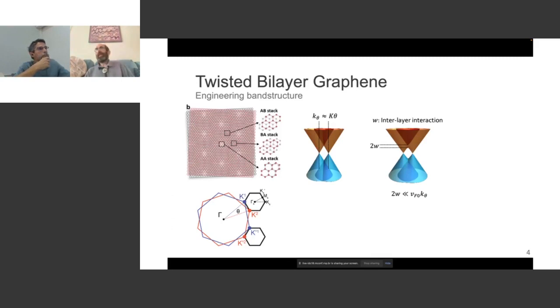So why is that more than a curiosity? It's because having energy independent of momentum upends the paradigm that we use to understand electrons in ordinary metals or semiconductors. So ordinarily, we have energy that is a strong function of momentum, a strong function of wavelength of the electrons in the system. And what that means is that if we have a certain number of electrons filling a material, they will fill all the kinetic energy states, all the energy states in this sort of band structure up to a certain energy, and then you run out of electrons. So all the states below are filled, all the states above are empty, and that turns out to be a very powerful way of understanding electronic properties of materials. But if energy is independent of momentum, then how do we decide which states electrons should fill and which states should be left empty?